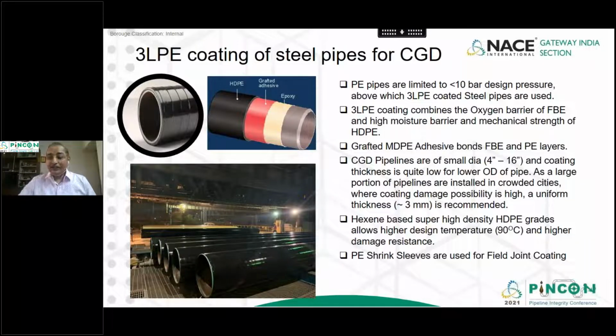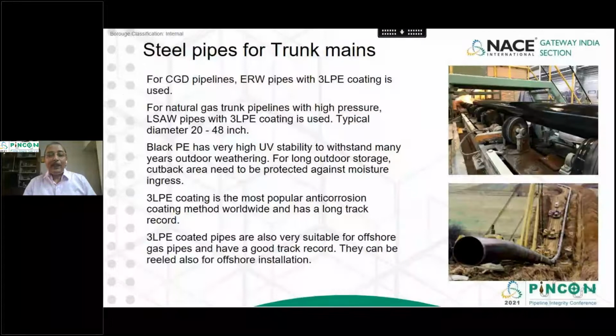Polyethylene shrink sleeves are used for field joint coating. Now for CGD pipeline of smaller diameter, ERW pipes with 3LPE coating are used. For natural gas trunk pipelines with high pressure, LSAW pipes with 3LPE coatings are used. Typical diameter is 20 to 48 inch.